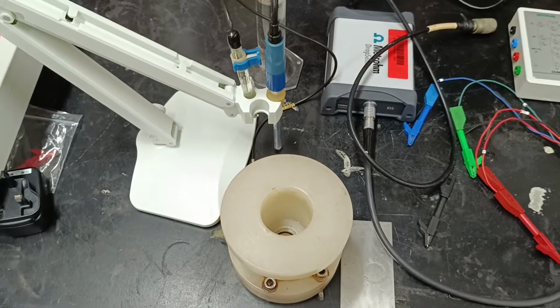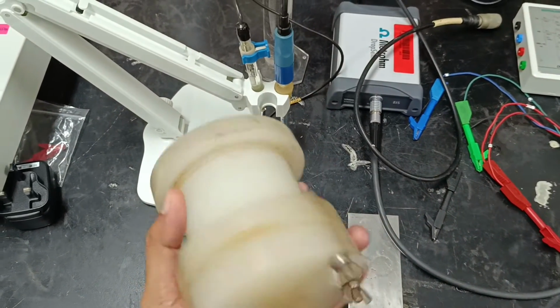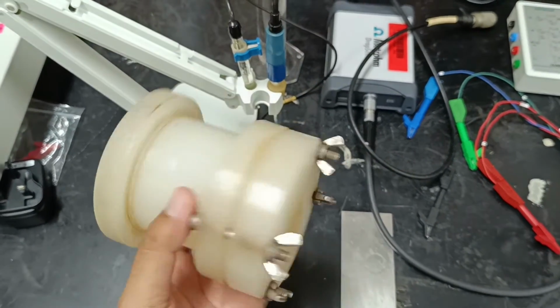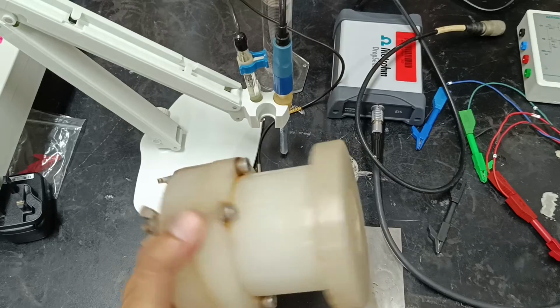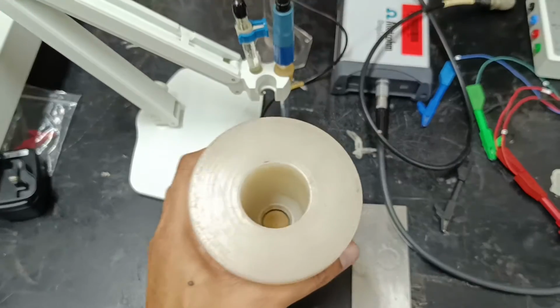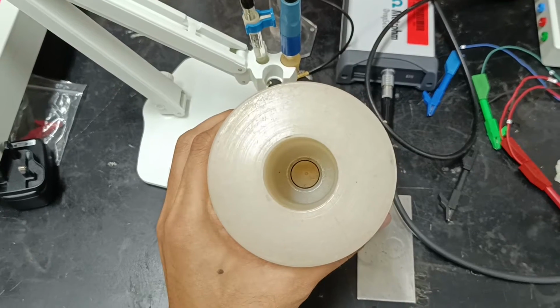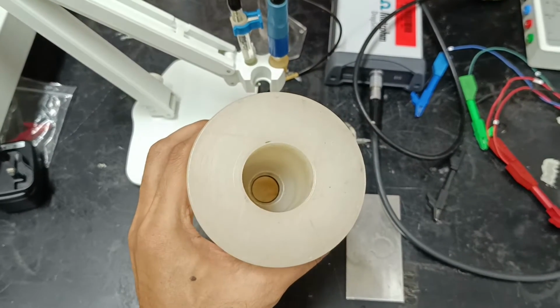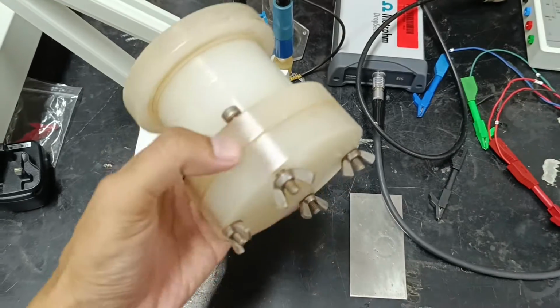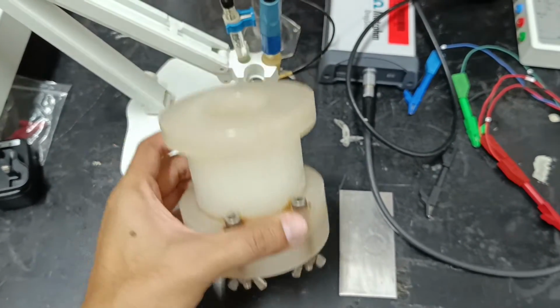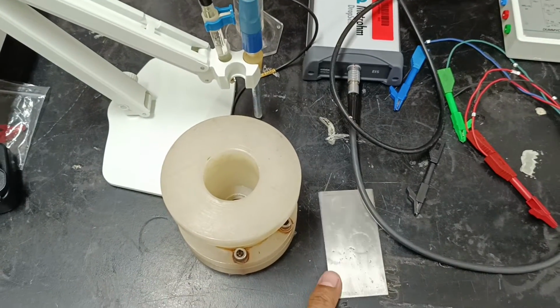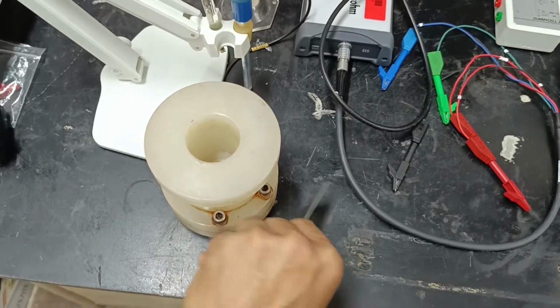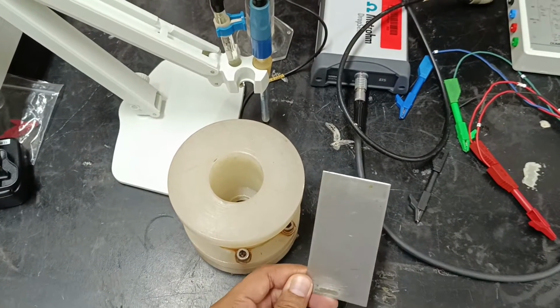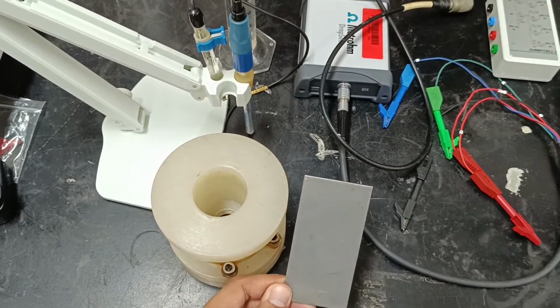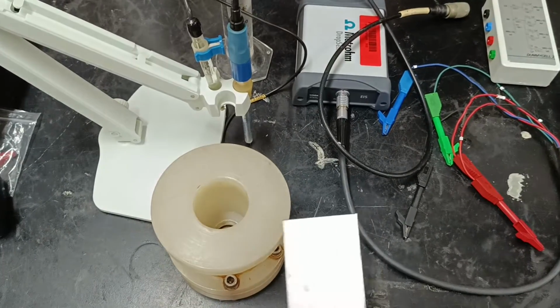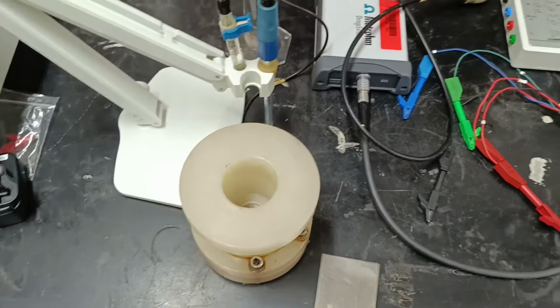Okay, so for the experiment setup, I'm going to use a cell here. If you want to know more about the cell, I have mentioned it in my previous videos. It is made from Perspex and it has an exposed area of around 2 centimeters diameter at the bottom. So the idea is you slot in the metal underneath. This is the metal that I'm going to try. It's stainless steel. It has quite a good surface, and we are going to slot it inside the cell.